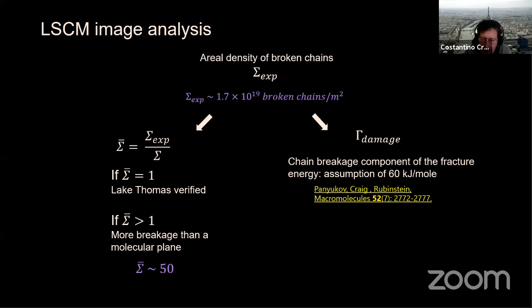And so a recent paper, where Stephen is a co-author, argues that on average, you could still break chains at a much lower energy, around 60 kilojoules per mole. And we are going to use that value in our estimates. But of course, this again has its imprecision. So if we use 60 kilojoules per mole, the energy that we get through damage in this particular case close to the glass transition is 250 joules per mole, about 10% of what we measure in terms of fracture energy. So we measure 2.5 kilojoules, and the bond scission can account for about 10% for this particular example.